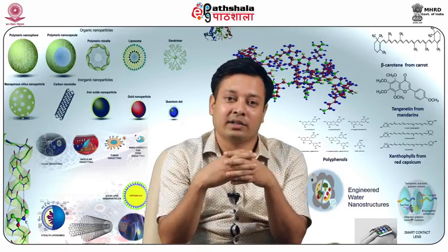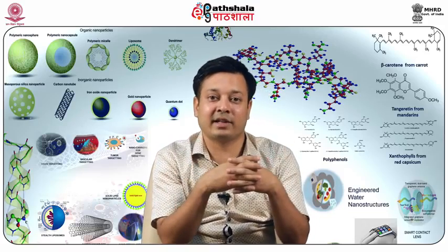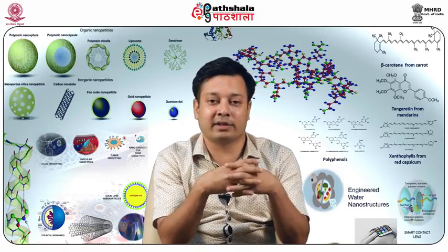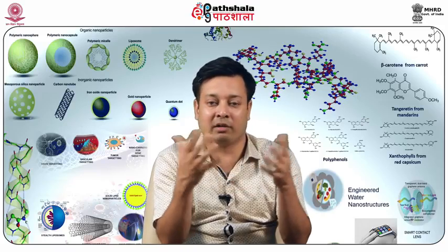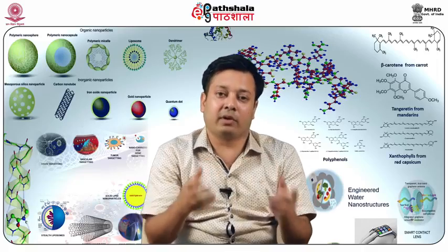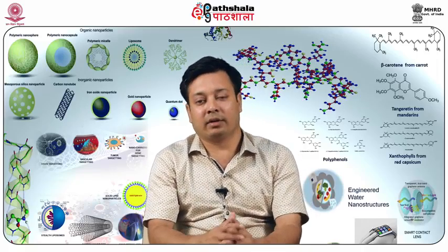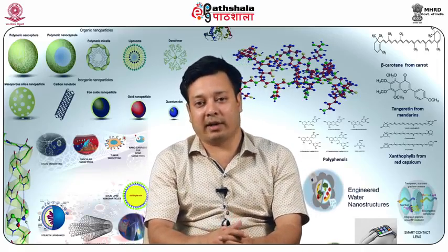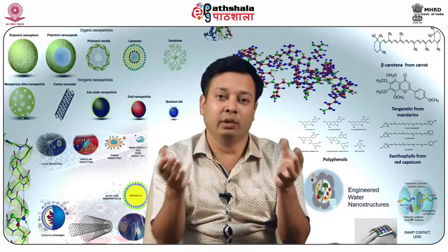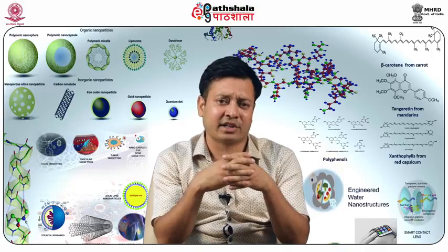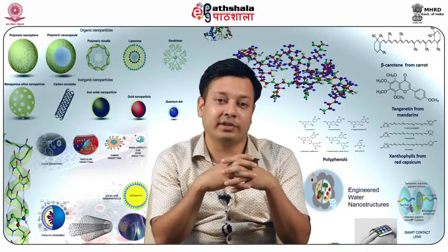If you take CTAB or SDS micelles, which are ionic, you would hardly get an aggregation number of something like 70, 100, 200 at maximum. But if you take Triton, which is a non-ionic micelle, the aggregation number will be in the thousands.